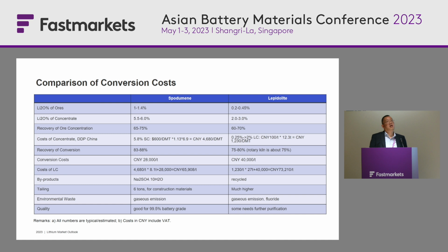In Talison's case, you can do over 70% because of the higher feeding grade. In China, we do flotation. So typically, we believe Chinese concentrators do a better recovery than our Australian peers. Typically, we think Chinese can do 5 to 10% higher in recovery by this flotation, okay? But for lepidolite, because of the lower feeding grade, basically, you get 60 to 70%.